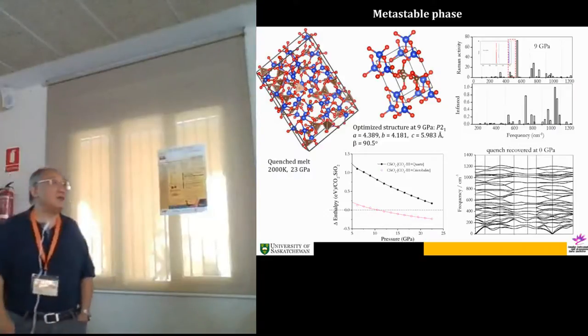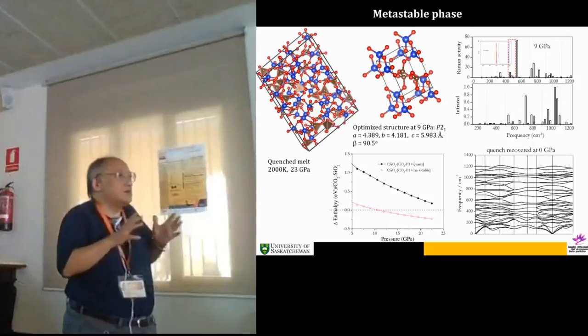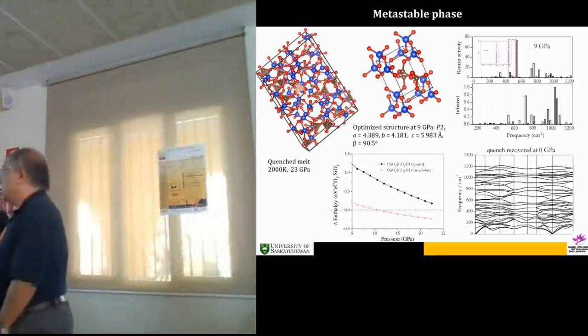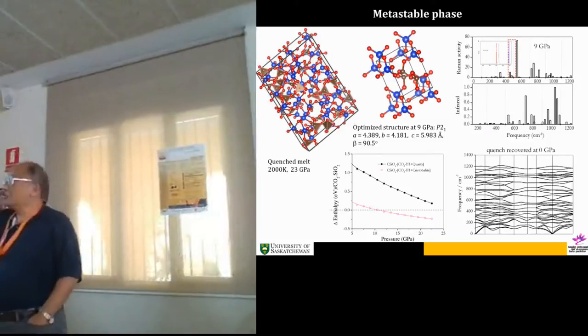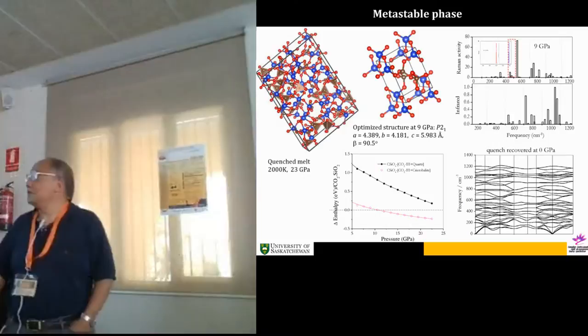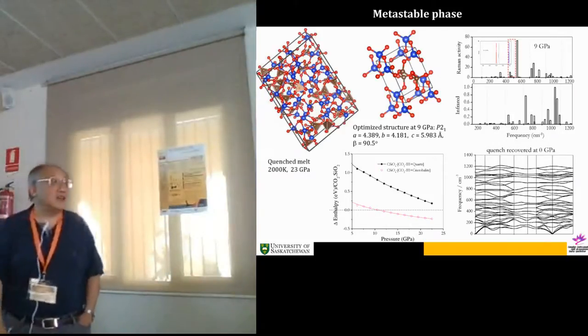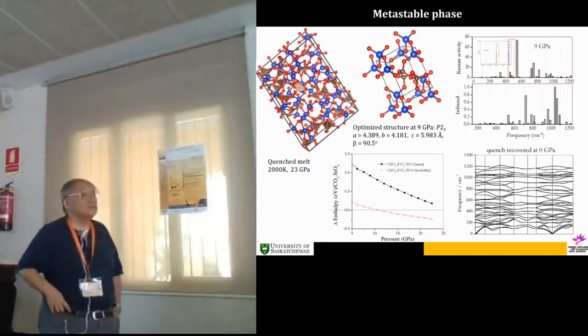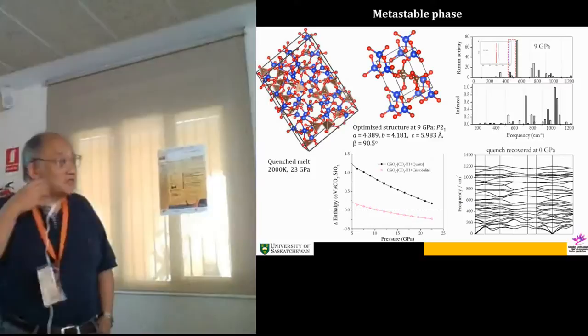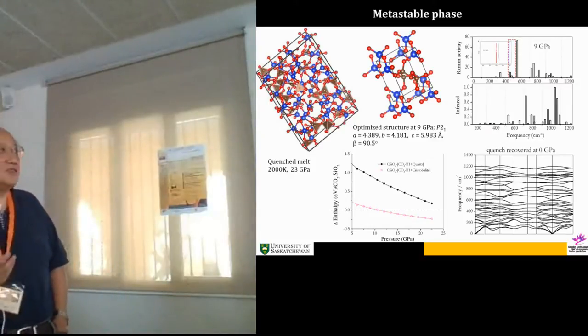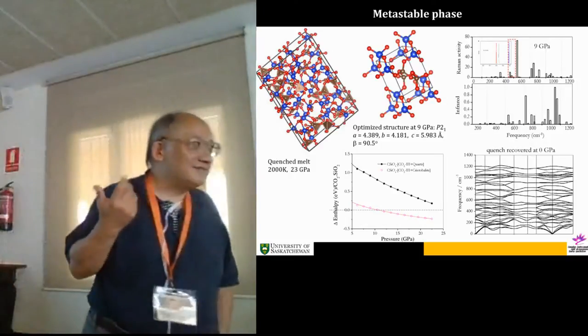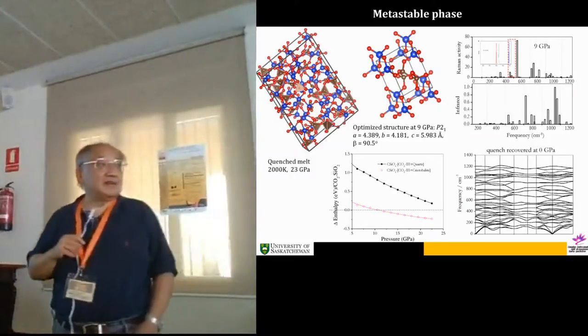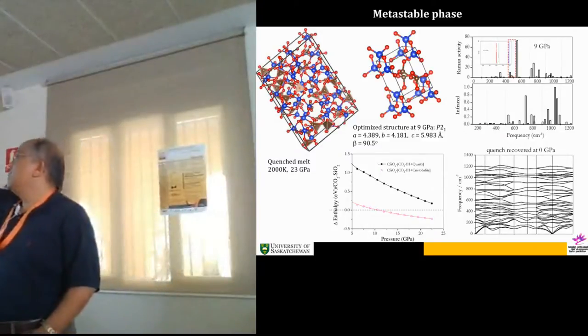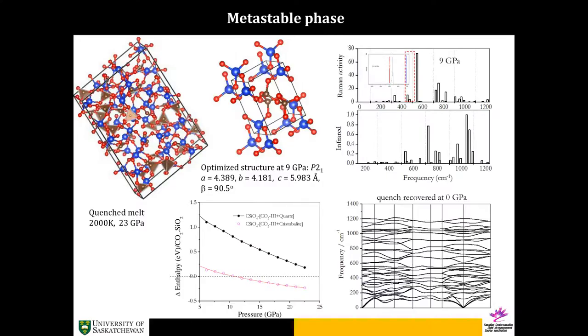So there's an optimized structure at 9 GPa. You look at the beta angle, it's 90 degrees. Because I have no disordering. My system, all the positions of the atoms are in their ordered positions. So it distorts tiny, 0.5 degree, from 90 degrees. You calculate the equation of state, it's definitely more stable than a CO2 plus an SiO2 cristobalite. So it's a stable compound. I totally did not expect that. I would think it's unstable. This material, actually, you can recover it at zero GPa. All right? So we reproduce a characteristic Raman and infrared spectrum. That's all you can do right now, all standard codes will give you the Raman and infrared intensity. And that really helped us.